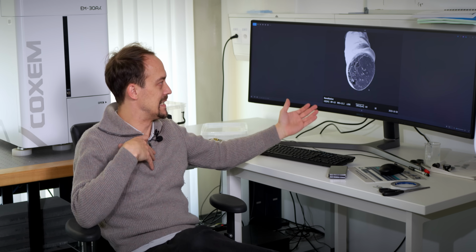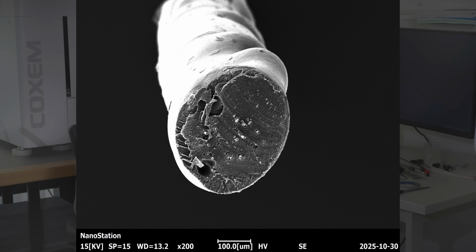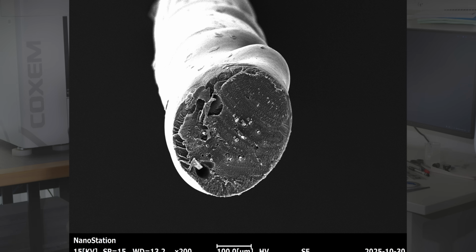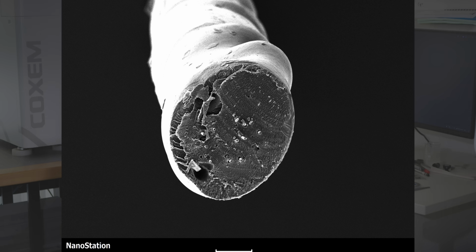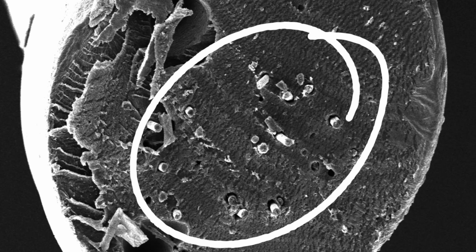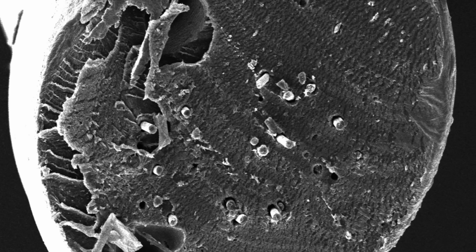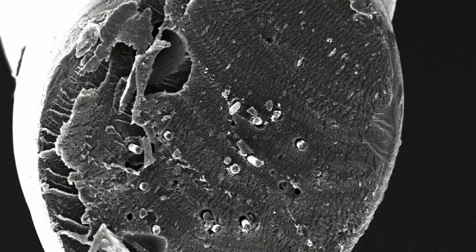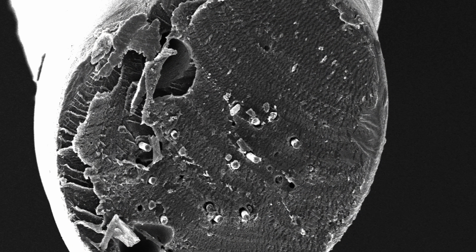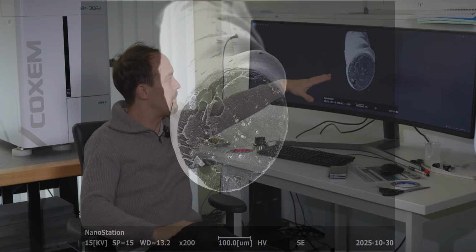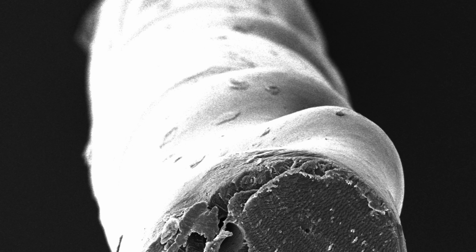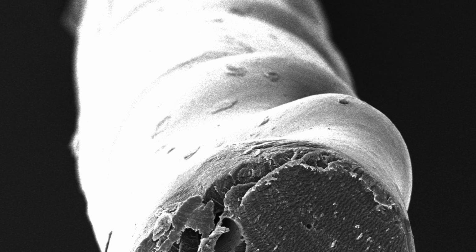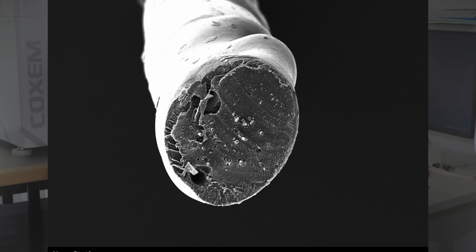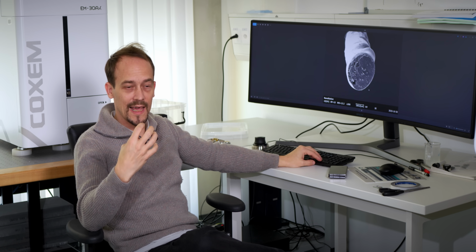What is a big surprise to me is actually this image. So this is an extruded strand of this coextrusion PLA. And as you can see, the carbon fiber actually stays in the middle of the extrusion. Something I didn't know, I didn't believe in, but it actually stays in the middle and you have an undisturbed layer of PLA still around it after it went through the nozzle. So that's really awesome. You can also kind of see in the background, where it fades out, that the PLA itself is very smooth. So you don't have carbon fiber sticking out or disturbing the layer around it.